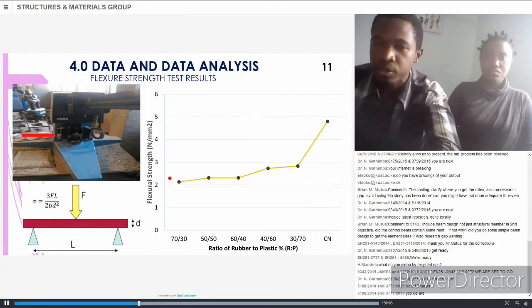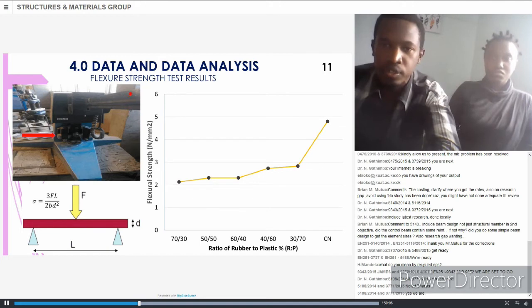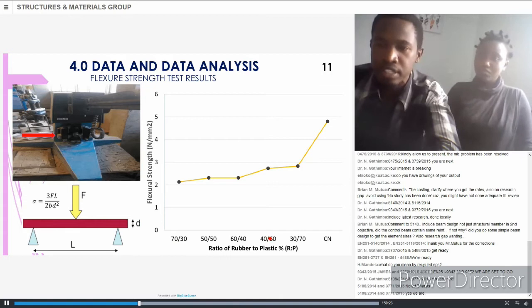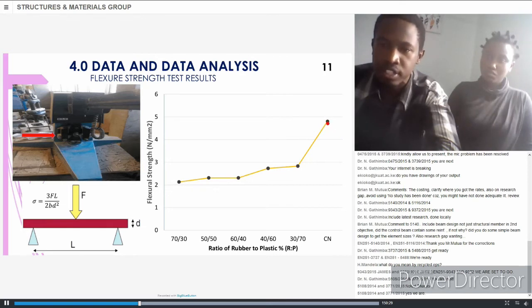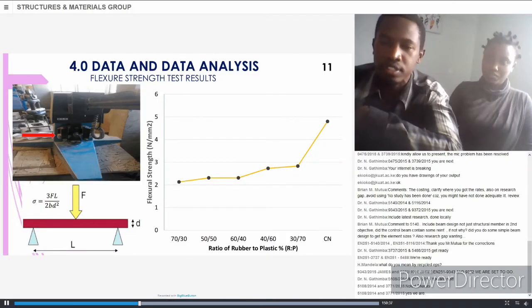Once we did the compressive strength test, we went ahead and did the flexural strength test. We inserted the flexural beam in the apparatus shown in the slide, and it was subjected to the 3-point bending method. The flexural strength test showed that with an increase in the percentage of plastic, the flexural strength also increases. And the control experiment had the highest flexural strength. That is, the control had normal aggregates, sand and stone, with 10 millimeters as the maximum aggregate size.